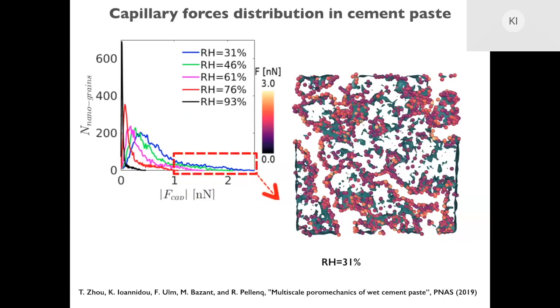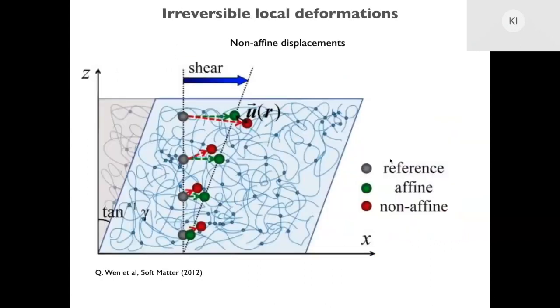So then, okay, we know that overall the magnitude of the forces is not strong enough to destroy cement, but let's see if these particles that have high forces can have local events that might be the precursor of cracks. To answer this question, we went further to understand the irreversible local deformations of this material, and to do so we use what are called nonaffine displacements.